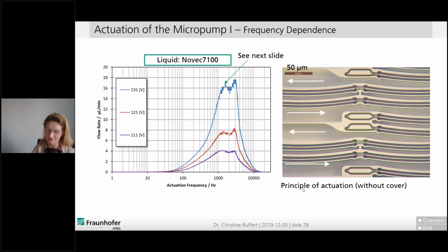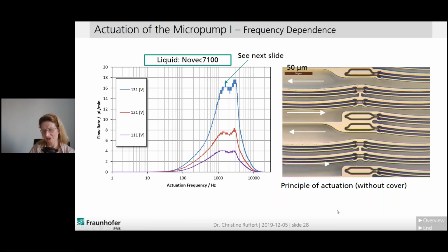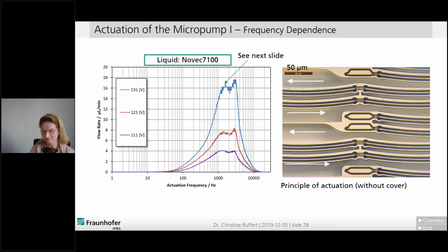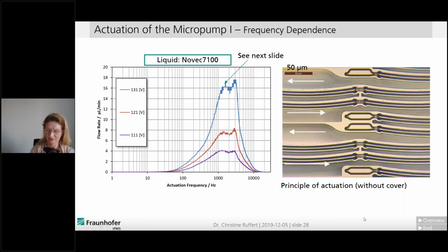But before, I would like to show you the principle of actuation here. So we have a real system. The scale is 50 micron, and the liquid is normally passing here and then coming back here, like a meander. Of course, we cannot pump liquid here because we would have to put a cover on, and then we cannot see anything anymore because there's a silicon wafer on top. So we just show you the principle of actuation without cover, without liquid and without the ability to create a pressure in these chambers. You see the cantilevers moving, and for the pump, we have to put a cover on top to create a pressure in the chamber.